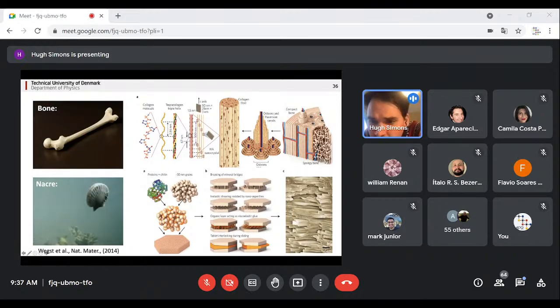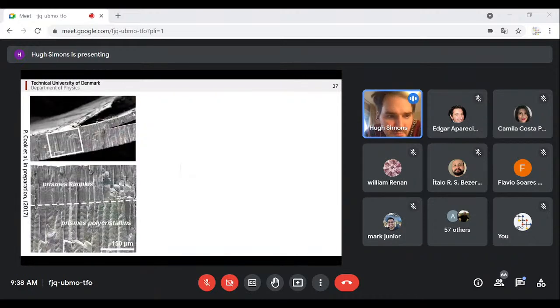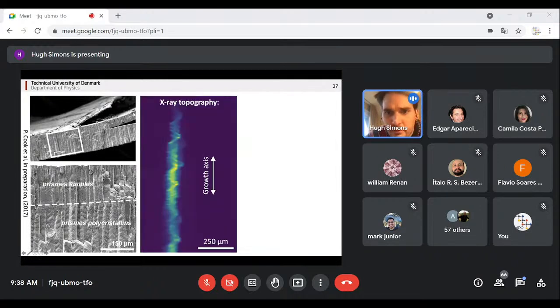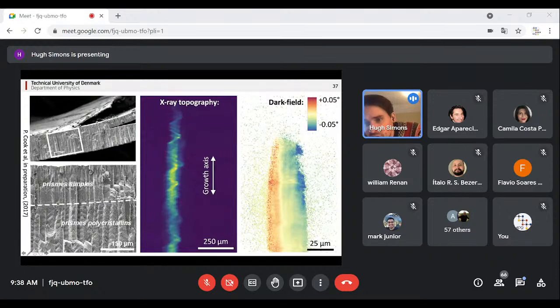And then if you consider what the shells are actually made from, this nacre crystal is in fact not very intrinsically strong. It's the fact that they're held together by these mineral bridges, and they form these multiscale structures. And this is really the origin of their strength. And so inside these kinds of structures, they tend to form these polycrystalline prisms. And actually, this is also one of the early tests of dark field microscopy, that we're able to not just see how these prisms are aligned, but actually even see the internal structure and the strains that happen inside them.